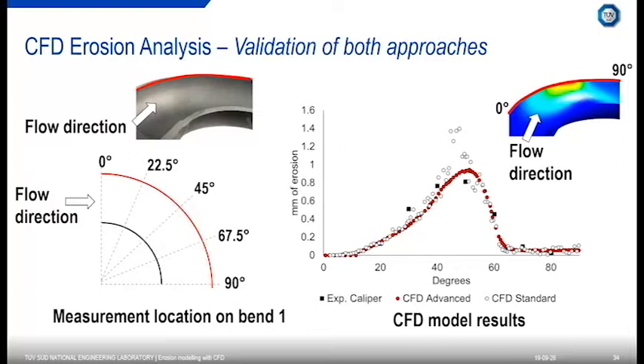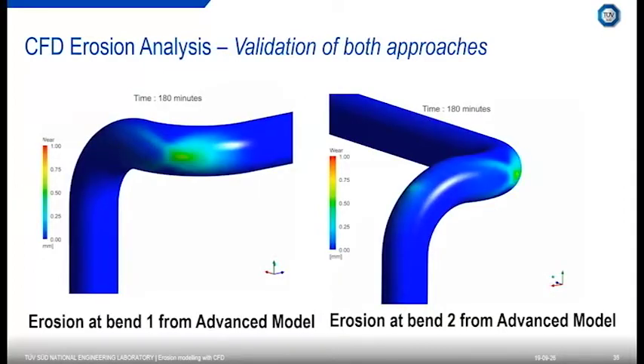Whereas with the advanced approach, the erosion might start off quite severe to begin with, but as we are eroding away the pipe bend, it alters the fluid velocity and slightly changes the particle path. So we actually have a reduced rate of erosion there too. And we can plot this as it evolves throughout the time of the test. The total time of the test is 180 minutes, and you can see here that the erosion is gradually increasing. What happens is it happens predominantly on bend one, and then it starts to get more severe on bend two. And what's really important as well is predicting where these particles go and how they rebound,